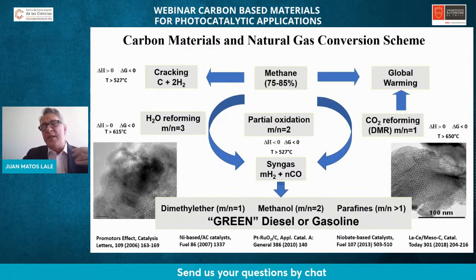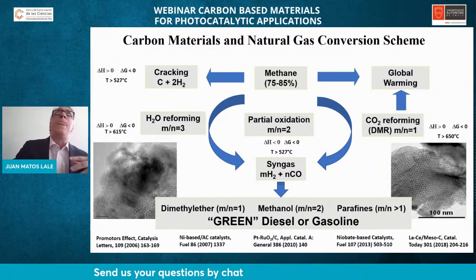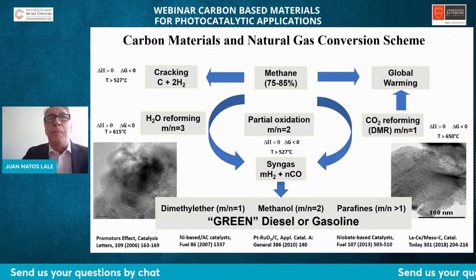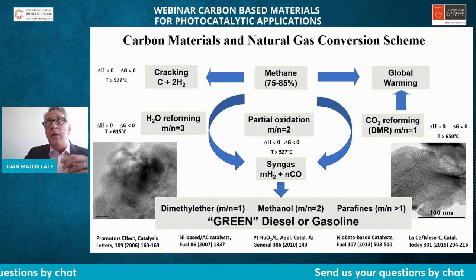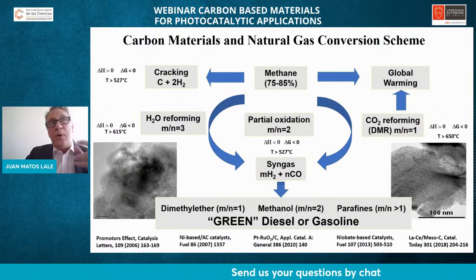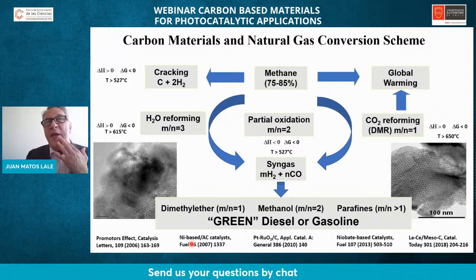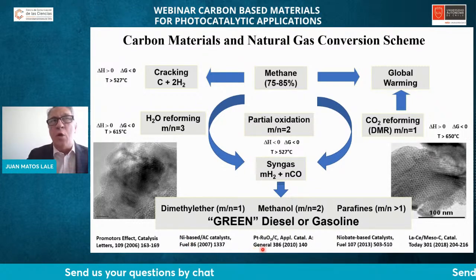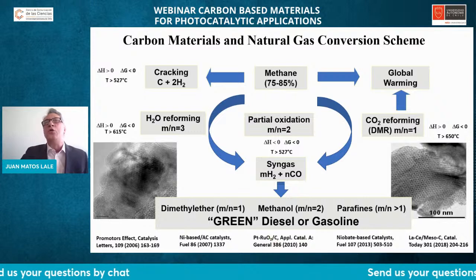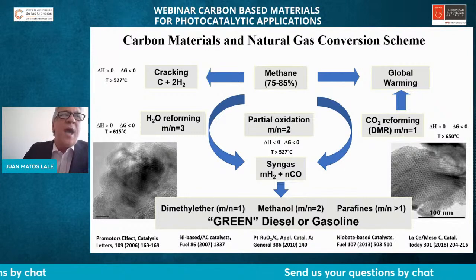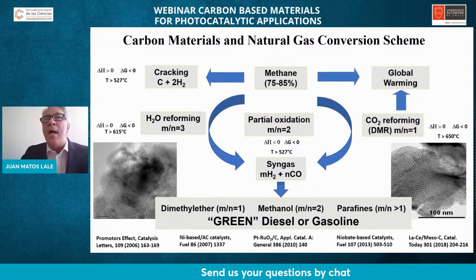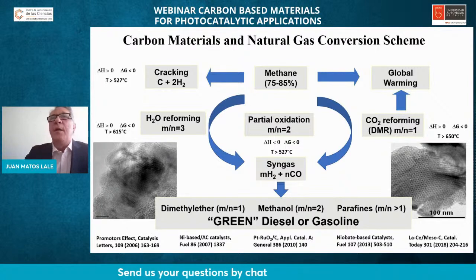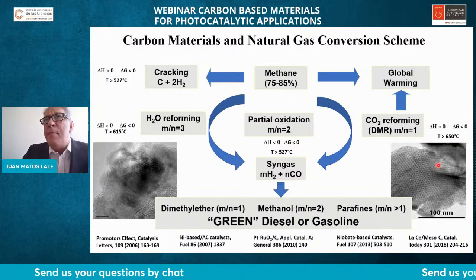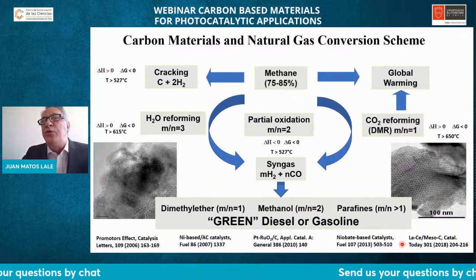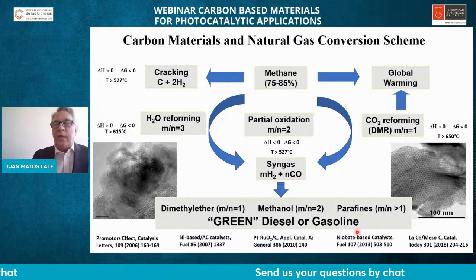We have explored the different possibilities with catalytic promoters. We have optimized the operative parameters using nickel-based catalysts. We have explored noble metals such as platinum or ruthenium. We have dealt with very acid catalysts such as niobate perovskite-type catalysts, and we even explored mesoporous pillared carbons using lanthanides and cerium catalysts.